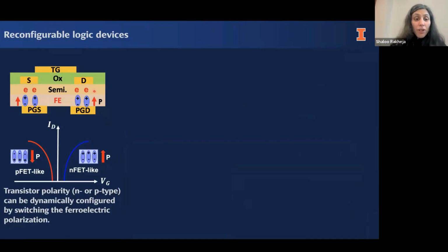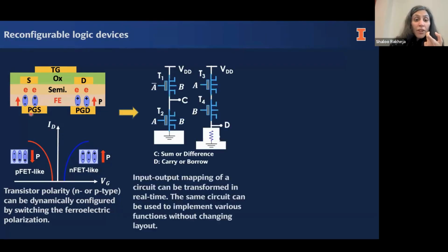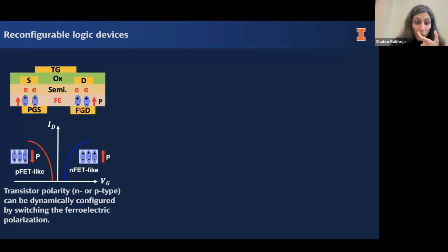So this is the semiconductor, right? The polarity of the charge carriers in the semiconductor determines whether this is N-type or P-type, right? So what we have done here, we've put a ferroelectric layer, and these are program gates embedded in the bottom of the ferroelectric. When we change the polarity of the programming gates, it changes the polarization direction of the ferroelectric, so it can induce either electrons or holes in the device. So this is doping the semiconductor through program gates, through polarization of the ferroelectric material. It is not due to putting N plus or P plus dopants inside the material.